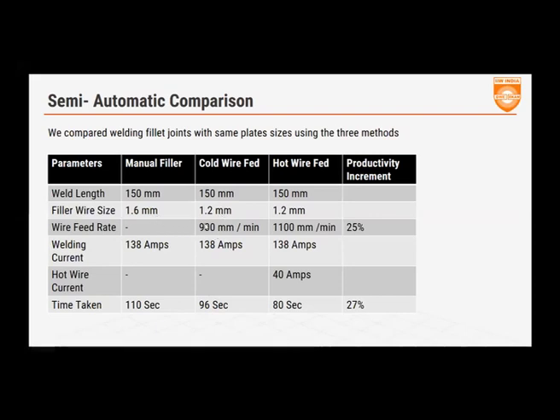Same thing when we added a little bit of hot wire to it and added about 40 amps current to the hot wire. You see the increase in the deposition, the wire feed rate went up to 1100 millimeters a minute. And the joint was able to be finished in 80 seconds. So a nearly 30% improvement on a 150 mm length.